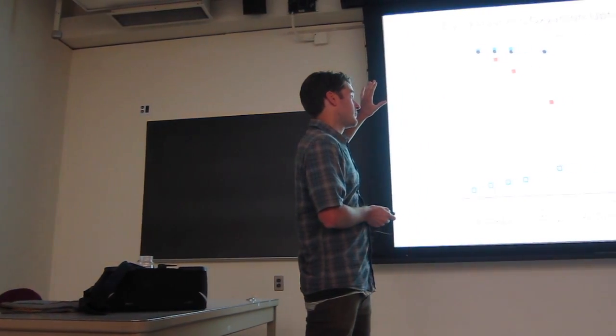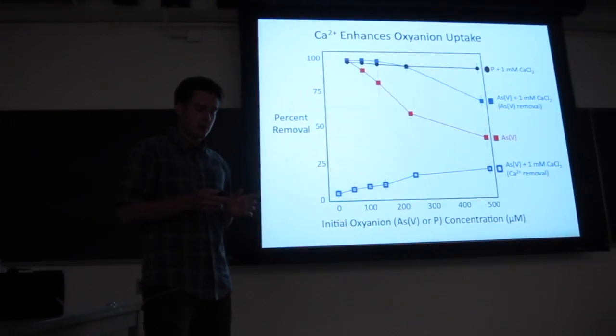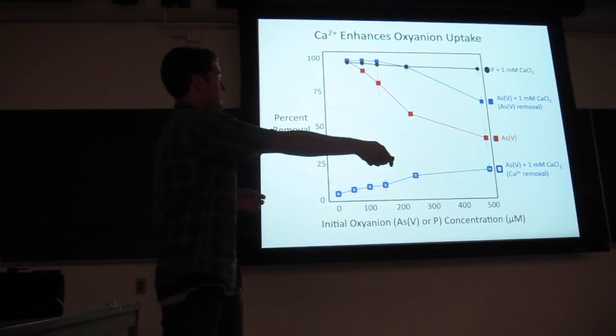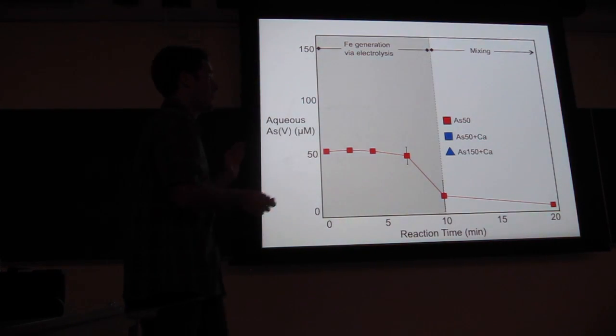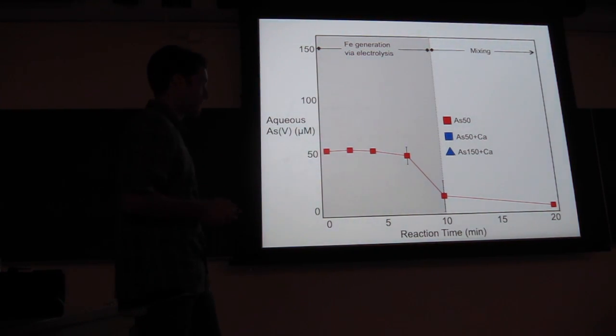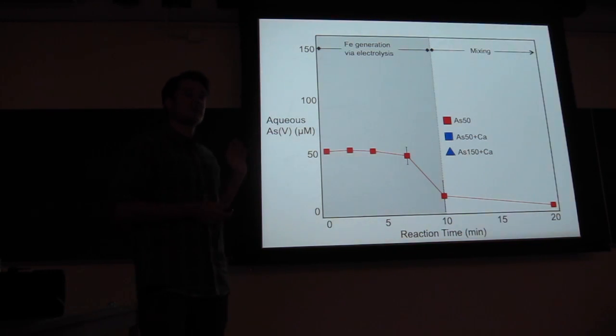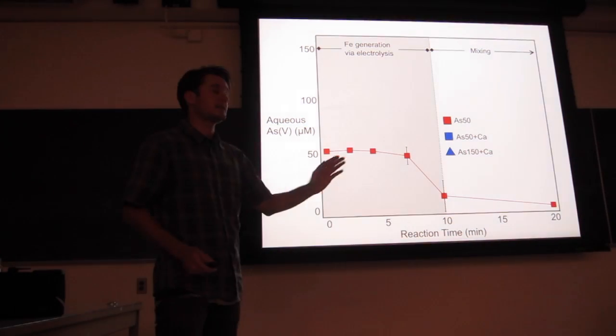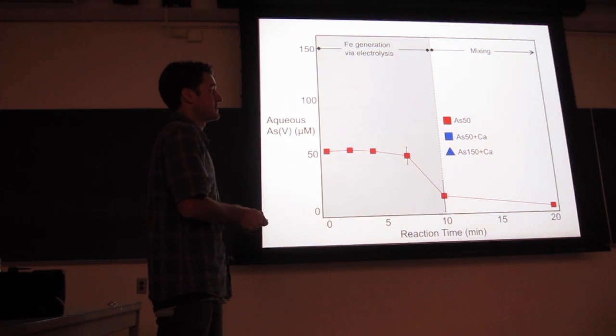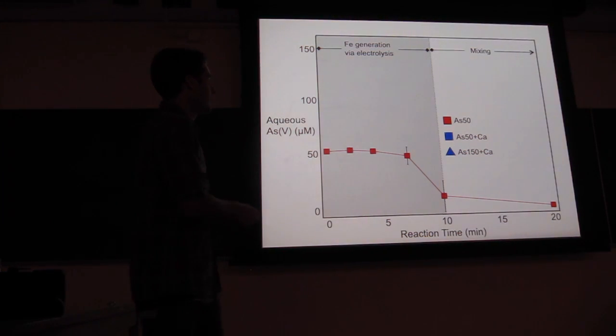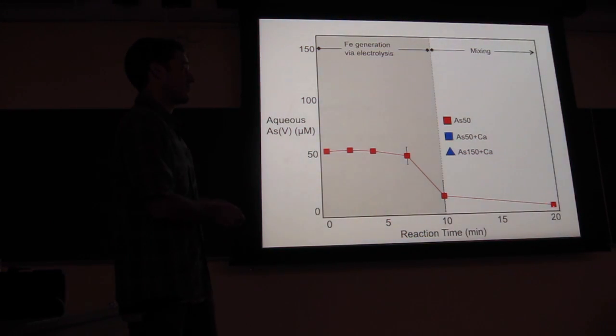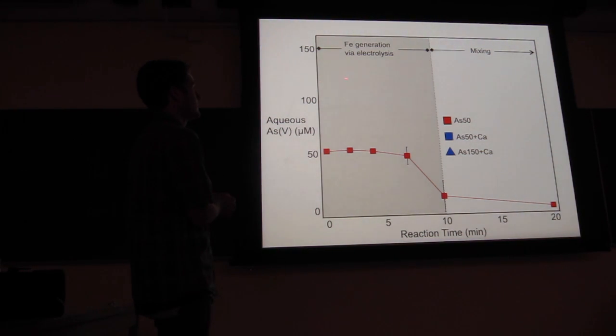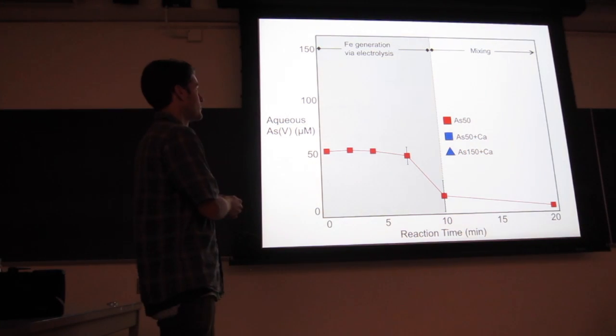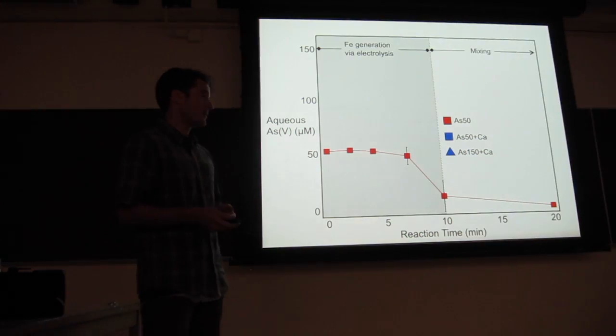So all of these experiments, the reaction mixing stage was 2 hours, and so in these experiments, we're going to look at all of those data points with a little bit more detail here. And so what I'm plotting is aqueous arsenic as a function of time throughout the electrolysis and mixing stage. And the mixing stage actually ends at like 2 hours, like way over here. But we can see that arsenic is essentially depleted at about 20 minutes. So keep in mind that the electrolysis stage is 10 minutes, so throughout this part, we're still generating iron.